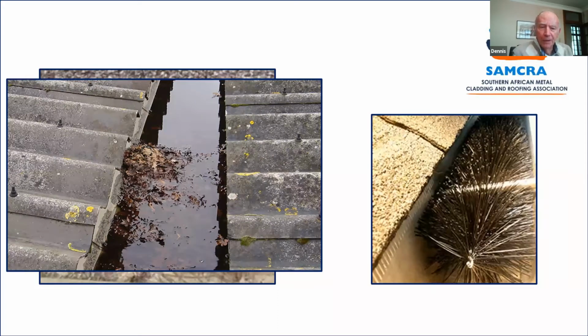Fortunately, the South African loading code 10160 part 2 calls for, under construction, 0.75 kilopascals UDL, and that will accommodate up to about 80 to 100 millimeters depth of hail, because fine hail packed, the mass of that varies between 500 and 600 kilograms a cubic meter. So it can become quite substantial, particularly where you've got a half sheet with a side flashing, where you could buckle the rib of the sheet there. So thanks for reminding me of that.